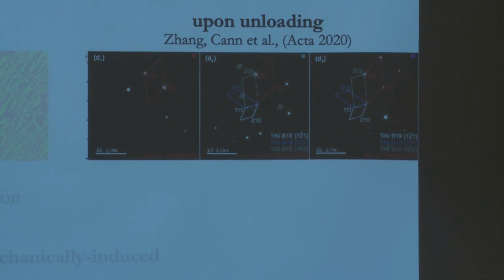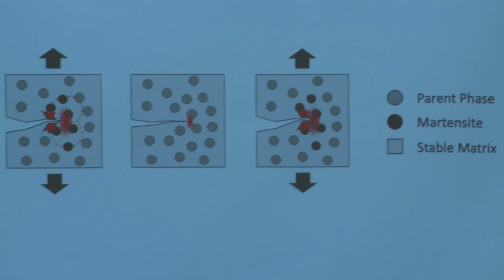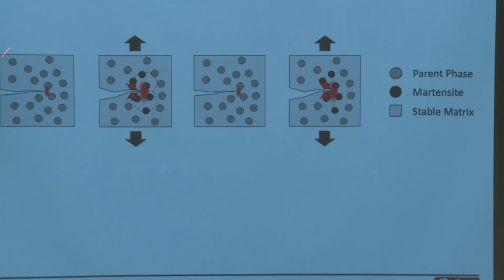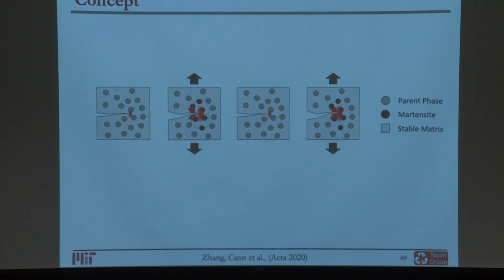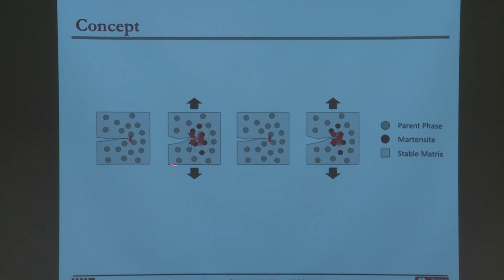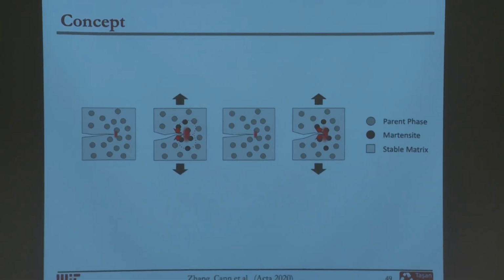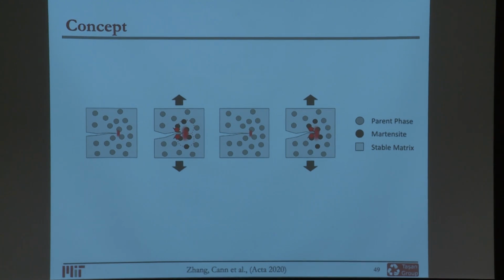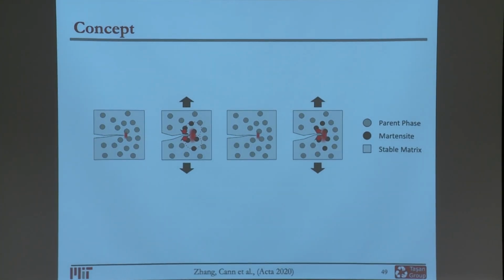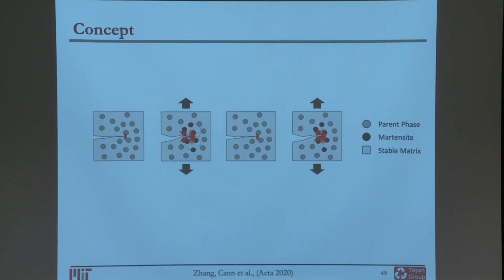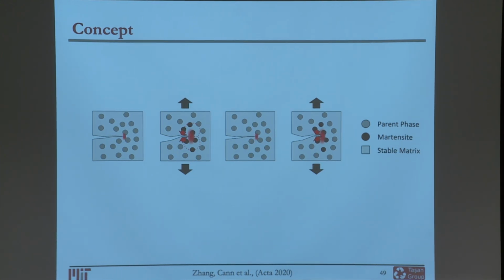So in the second approach, what we are looking at is a reverse transformation upon unloading. So this is a very different idea which is schematically shown here. So we are going to create a microstructure. This microstructure has the metastable phase again. So that phase is going to transform again. But now when we release the load, that phase is going to have a reverse transformation back to its original state, original crystal structure, original phase, I should say.